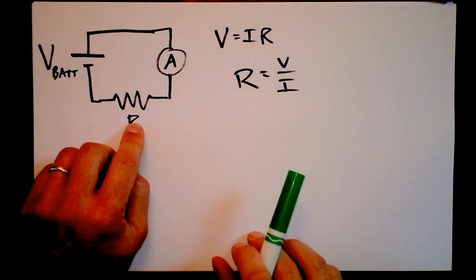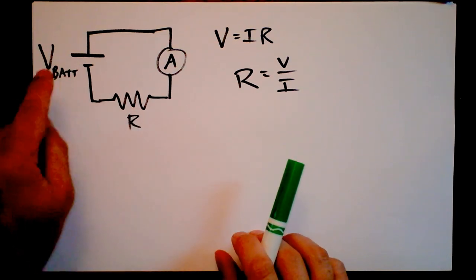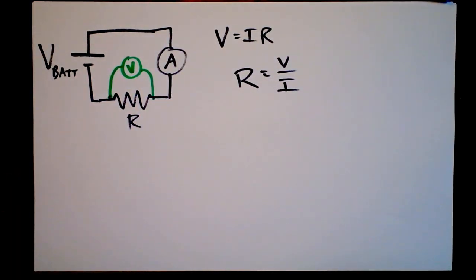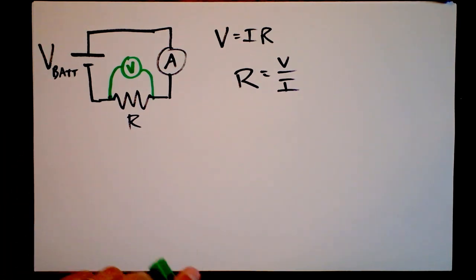Okay, so here's my point. If this is a small resistance, then we need to do better than just V battery. We need to get ourselves a voltmeter and stick it right here. And that becomes then really what that becomes is a four point resistance measurement.